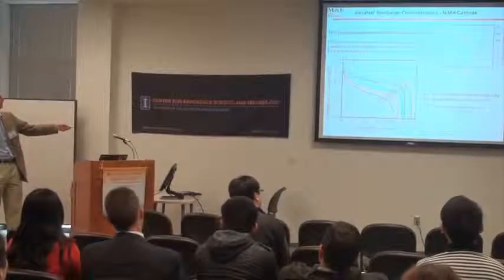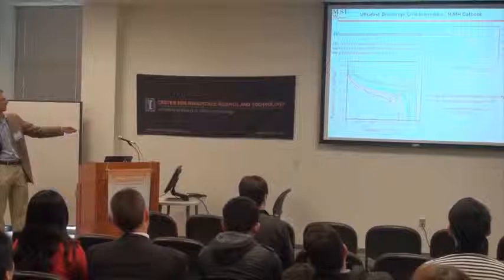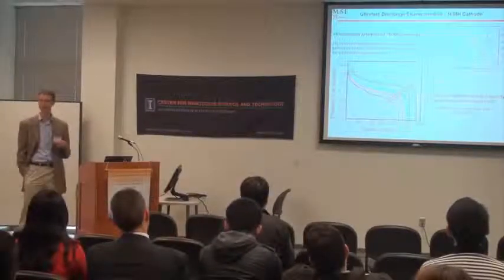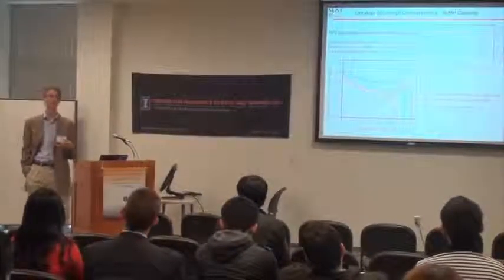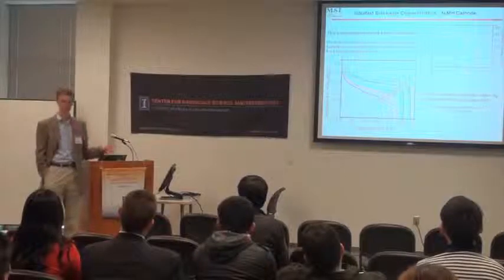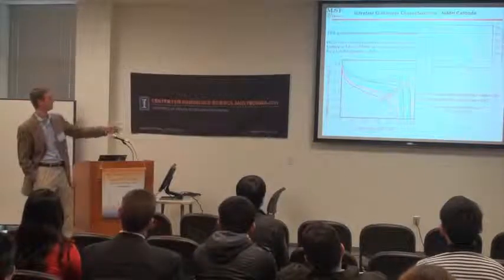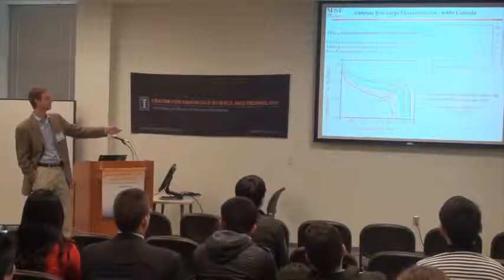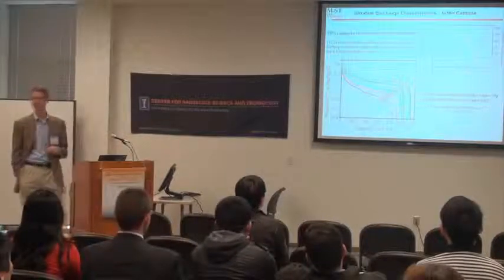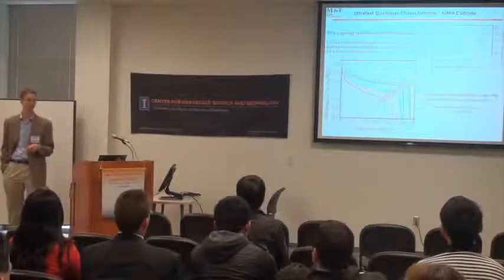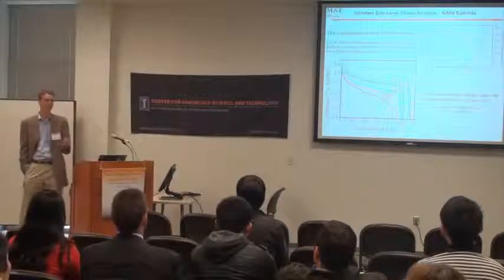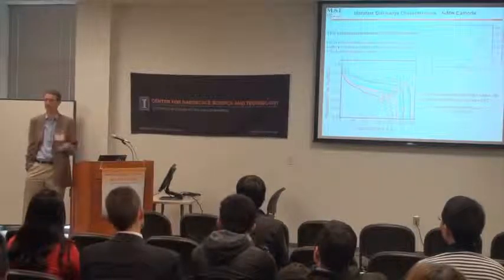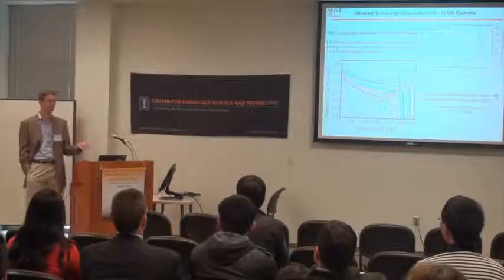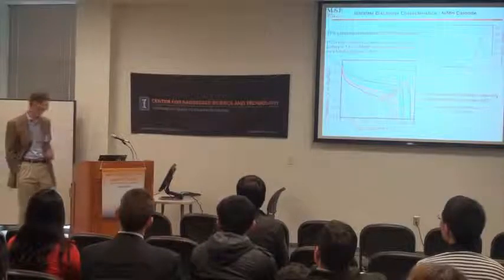But in this system here, we now discharge at 1,000 C. That's discharging the battery in 3 seconds. We discharge it in 3 seconds, and we still get 75% of the energy out. In a conventional battery, once you hit about a 2-minute discharge, most of the energy is simply dissipated as heat. All we've done here is, this is just Ohm's law. All the internal resistances are extraordinarily small, and so you can pull the power in and out of the battery quite rapidly.